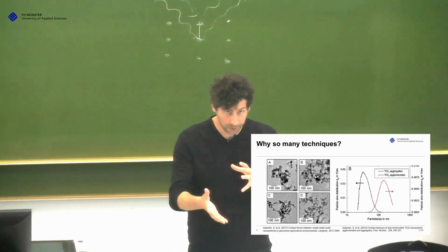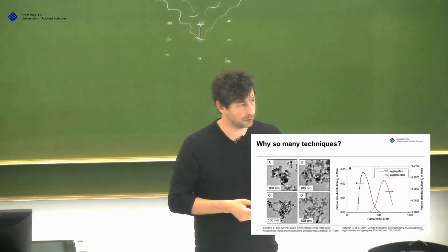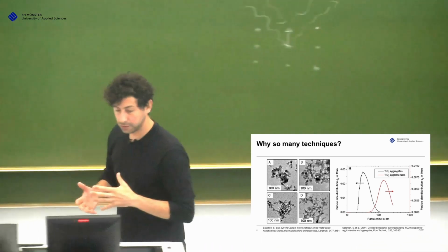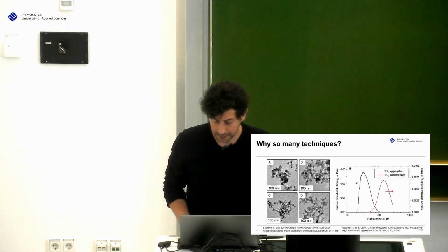It's different to the size of the TEM primary, but you see if you're in the good range. Then you make a BET, and then you see if your analysis is good or not so good. And in the best case, all three methods give you more or less, plus minus a few nanometer, the same size. Good, but I would like to know something about aggregates and agglomerates